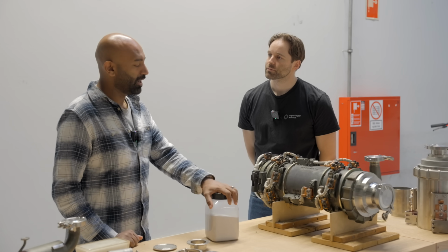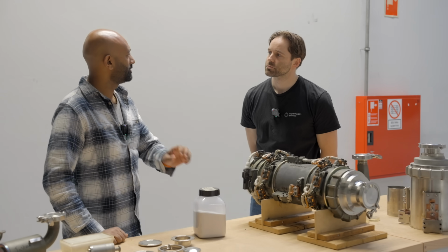So we create a eutectic of uranium and thorium separately with lithium fluoride to lower the melting point, and that lowers the melting point for uranium to 490 degrees Celsius and for thorium to 550 degrees Celsius. And so that means that when you go to 600 degrees, those are both liquid and are well above their melting points, and you can pump them around. So what happens to lithium-7?